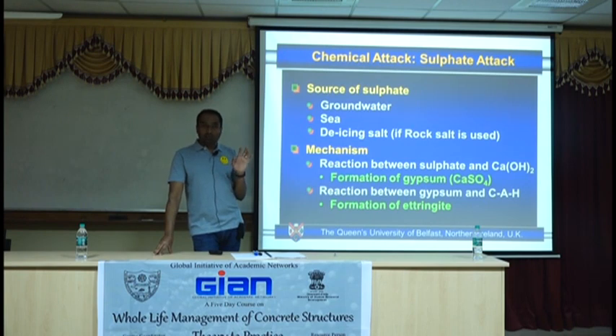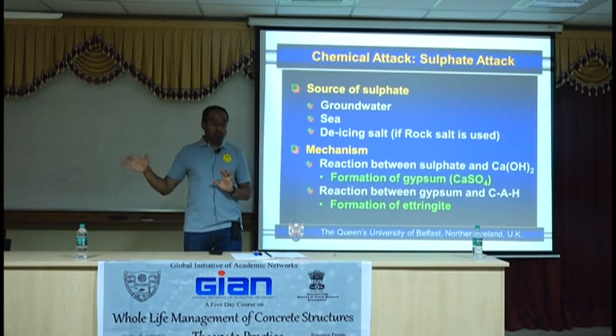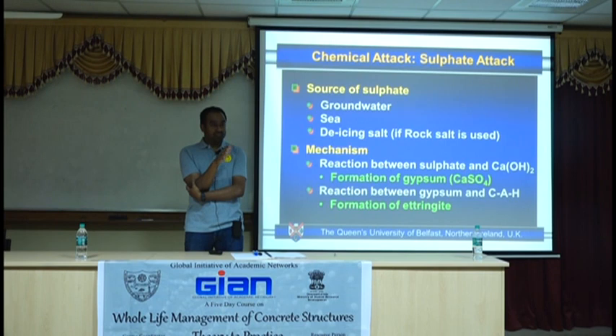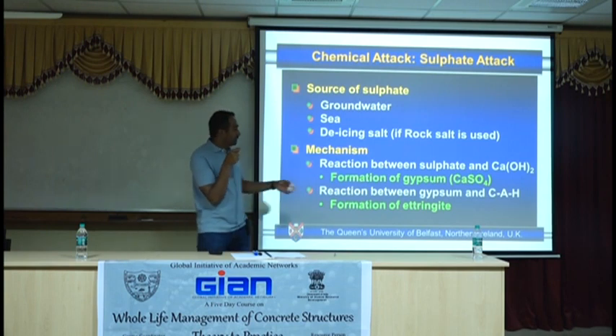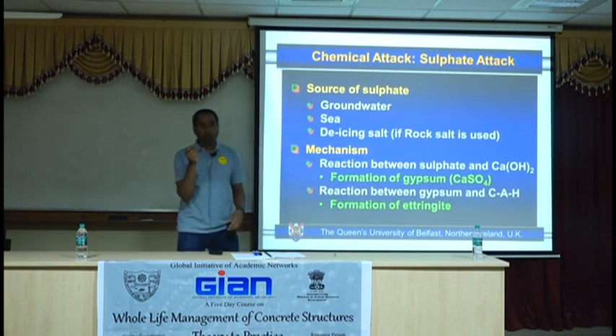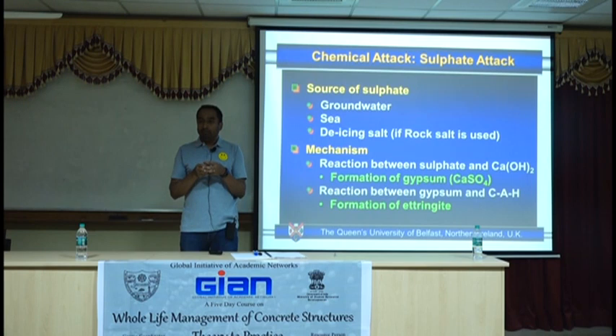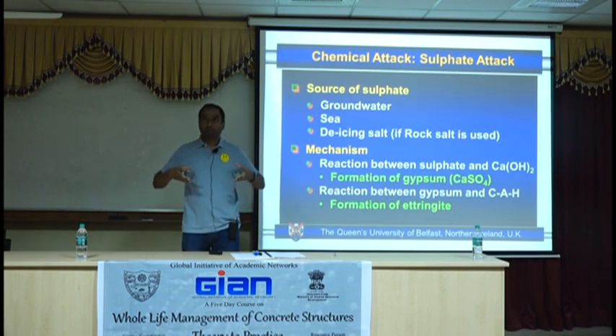The reaction is between the sulfate ion and the calcium in the calcium hydroxide. Together they form calcium sulfate. Calcium sulfate is gypsum — that you add to the cement clinker when you grind them for controlling the setting time, so it's something that cement already knows of. But calcium sulfate forming later on in the matrix has the same effect as a free internal reaction. The crystals need to be accommodated and they're quite big, strong crystals, which means it'll rupture the matrix.